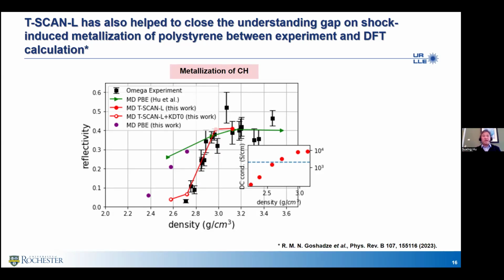Basically, it tells you that if you use a not accurate exchange correlation functional like a PBE, you will predict this molecule chains in the plastic will break up at a much lower pressure. So in reality, this carbon chain will exist at a relatively high pressure. That's why you will see the system become metallized at a later, higher pressure instead of the PBE predicted low pressure. So we're pretty happy that can make some difference.